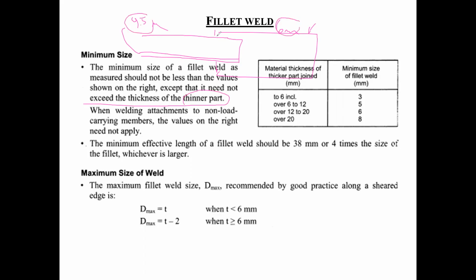So therefore I would specify nothing less than a 6 millimeter weld here. That's what they're saying. Okay, so if both thicknesses are the same, these are the minimum weld that you're using. If the thinner part has a smaller thickness, then you should not exceed the thickness of the smaller one. Okay, that's one thing. So that's what they're trying to make you say here.